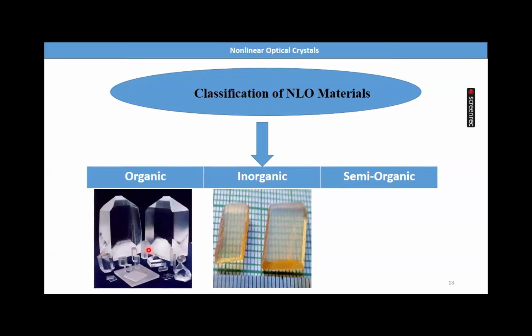And other organic crystals. There are a number of ideas that can help in designing organic molecules with significant optical nonlinearity. Second harmonic generation is a second order nonlinearity process that is impacted by crystalline arrangement and molecular structure in crystals. Studies demonstrate that extended conjugation, in the presence of a low-lying spectroscopic charge transfer resulting from electron donating and electron accepting substituents and an aromatic ring or related conjugated system, increases second order nonlinearities in organic compounds.